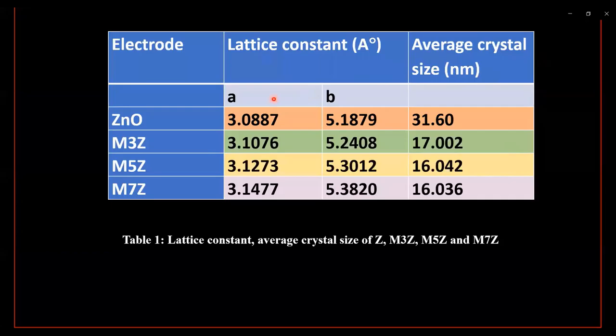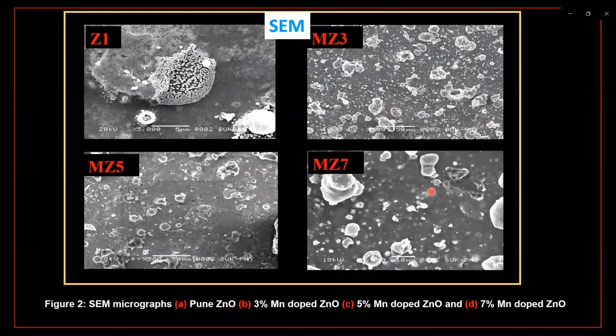The lattice constant and average crystal size were calculated with the help of XRD. Average crystal size goes on decreasing as Mn concentration increases. The SEM, scanning electron microscope, image shows spherical nanoparticle type morphology, which could afford superior surface area for redox in the electrode.